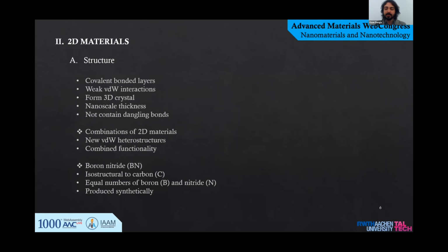All 2D materials are composed of covalently bonded layers held with weak van der Waals interactions to form a 3D crystal. And the weak van der Waals interaction does not contain dangling bonds. With this structure, combinations of 2D materials can stack in sequences to create new van der Waals heterostructures. And these heterostructures may even show combined functionality of the individual layers.